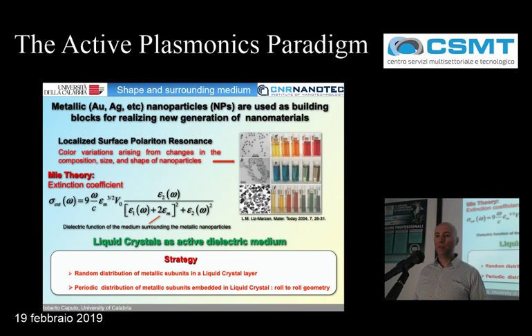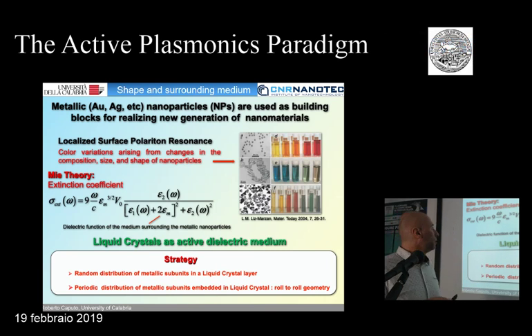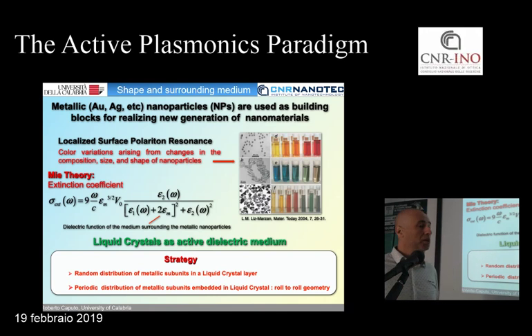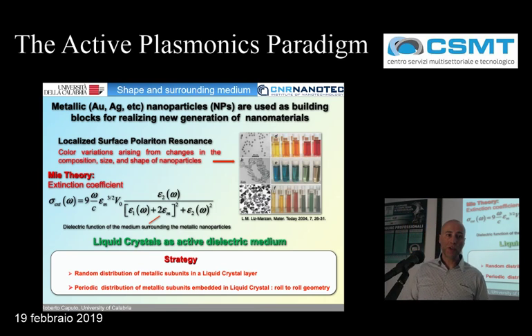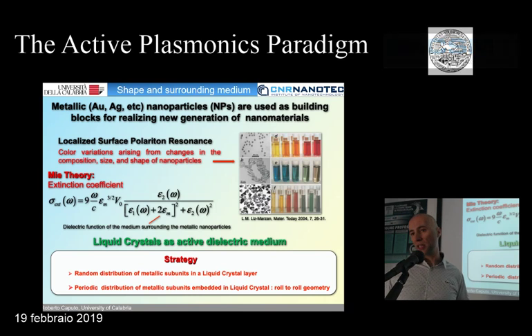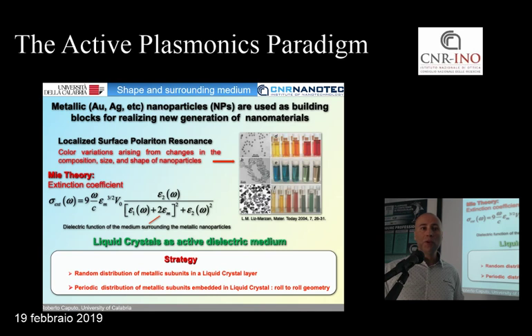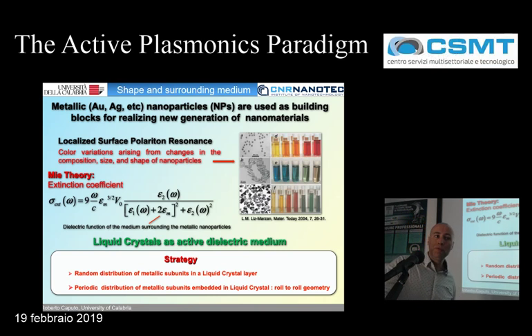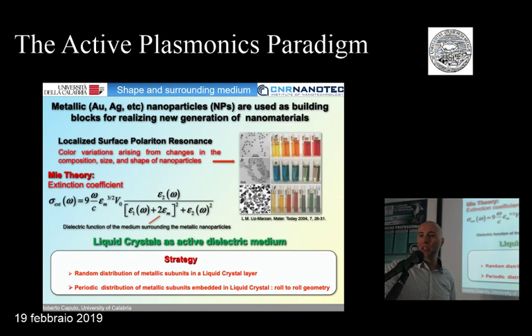So the main way to modify the plasmonic resonance is that the extinction cross-section of our system contains the surrounding medium of the typical system we are considering. So in this formula, we see that there is this epsilon m, which represents the dielectric constant of the medium surrounding our system. As you can see, because this constant is at the denominator of this equation, if you change this value, in principle, you are going to change the extinction cross-section of your material. And if the material you use to surround the particles is tunable, so you can change the dielectric constant of that material, in principle, you can influence the resonance of your system. So this is the basic way to obtain active plasmonics.